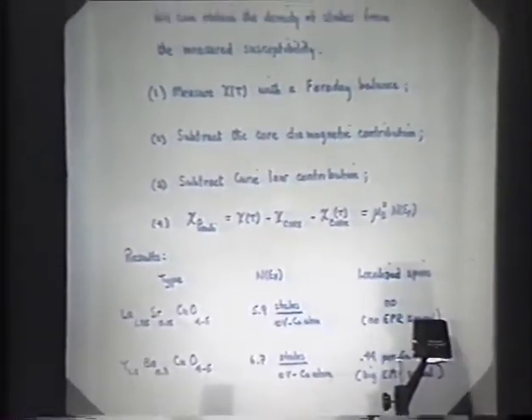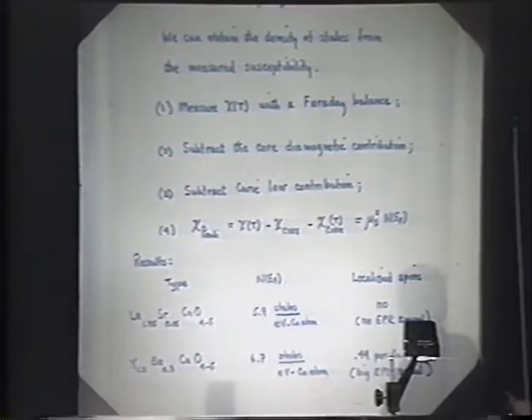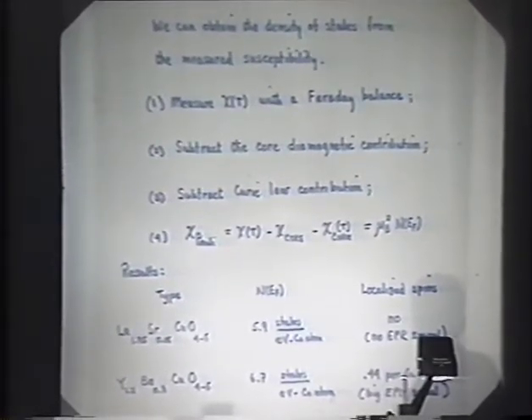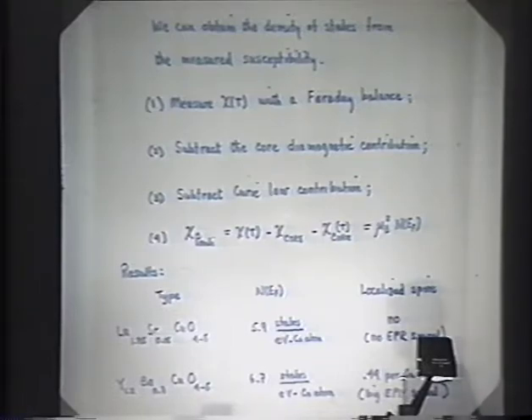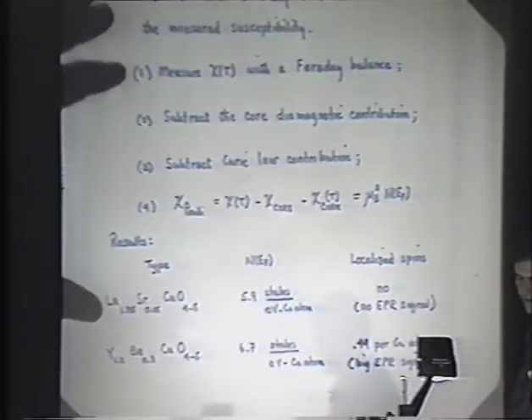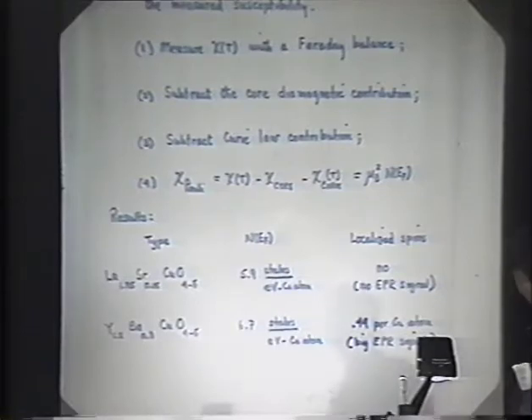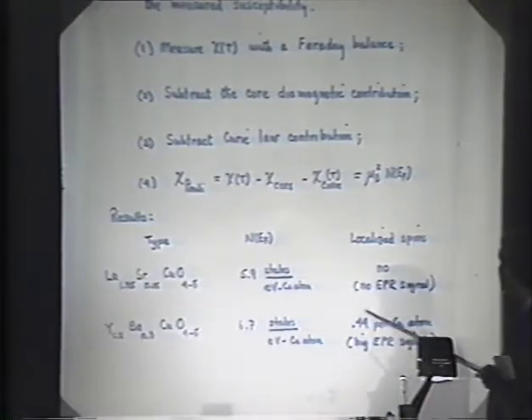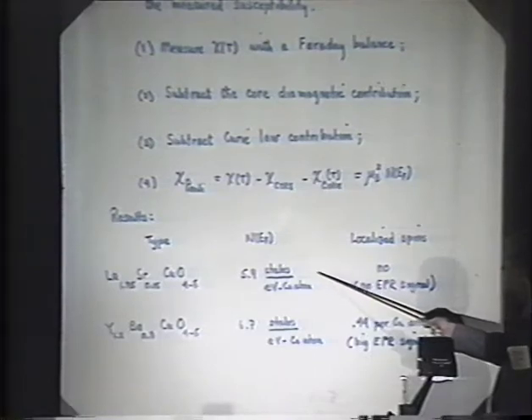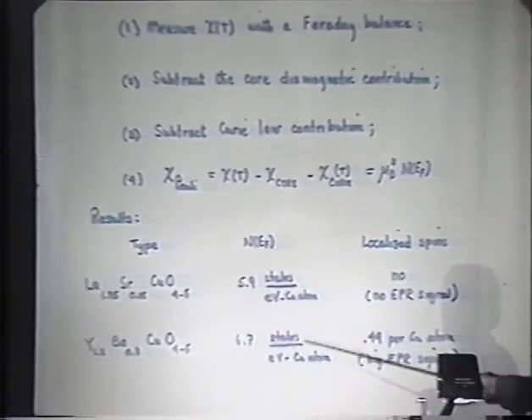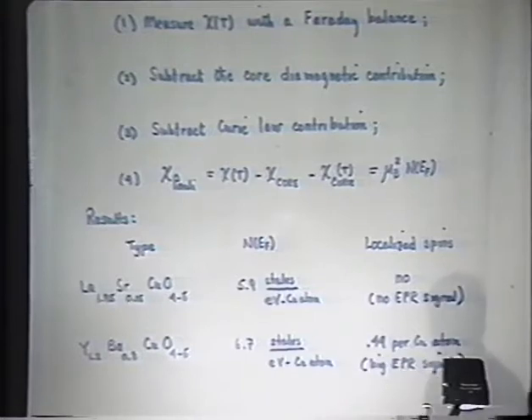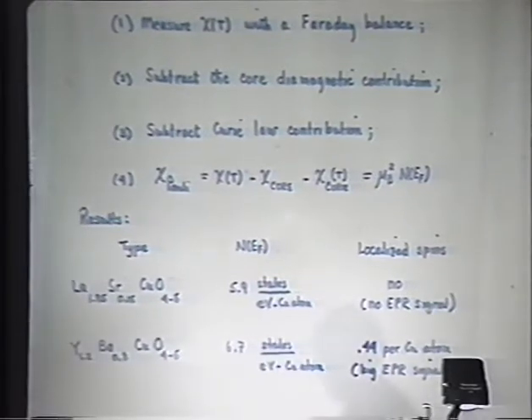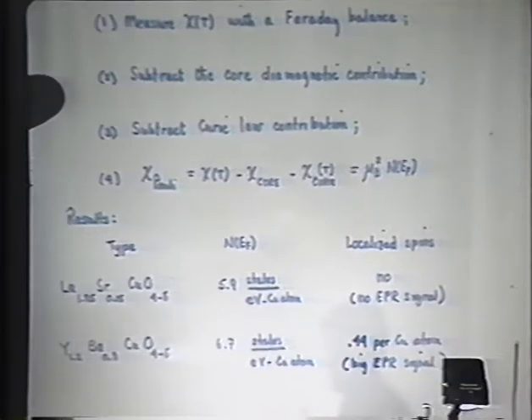In summary, we actually can extract the density of states from these measurements. We have to do a little bit of subtraction, but we can take away the core diamagnetic contribution and the Curie contribution, and equate that to the Bohr magneton squared times the density of states. When we do this, we get really rather large numbers for the density of states in the lanthanum-based oxides, and even larger density of states for the yttrium-based oxides. We also see no EPR signal in the lanthanum-based oxides, and do see a very strong one in the yttrium-based oxides, consistent with this paramagnetic contribution we saw.